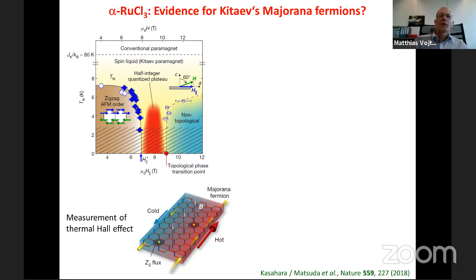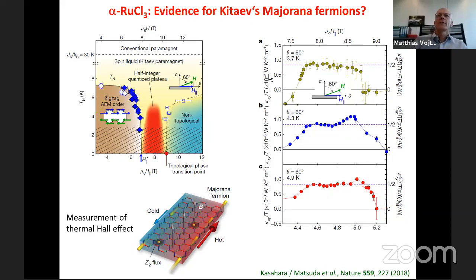And one can actually show that if there are quantized edge channels, as in the conventional Hall effect, then this thermal Hall effect is quantized as well. It's proportional to temperature, but if you divide the Hall constant by temperature, then you get a quantized number. And the number, again, is an integer, like in conventional Hall effect. Now, this measurement has been done in this particular material, and in this red regime here, one finds, and this is now this Hall constant divided by temperature as function of magnetic field, one finds it to be approximately constant in this red regime, and it is quantized to a number which corresponds to half an edge channel.